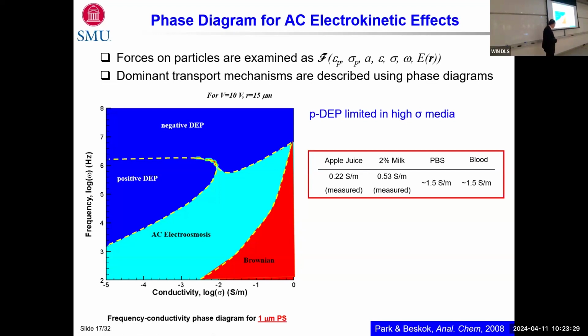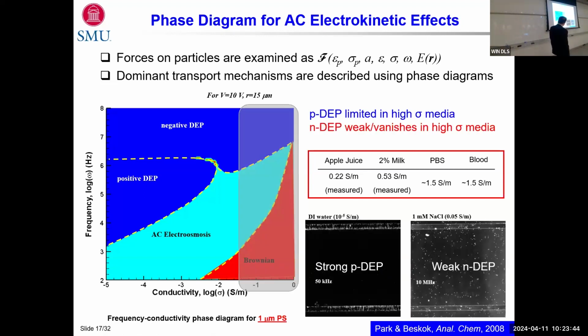We were trying to use this for sample concentration from apple juice and 2% milk. And those are basically the conductivities of those fluids versus blood plasma versus PBS solution. So obviously there are big differences. And you can actually see that in the DI water over here in low conductivities, I can see the very nice particle shading, but we lose the effect of DEP. We expected negative DEP, so I was hoping to see that these particles will be coming on top of the electrodes. These are electrode gaps here, but we didn't observe that. So obviously, DEP is losing its effectiveness, and that's a big concern because all physiological media is mostly like 1.5 S/m conductivity, and then this method may not be useful at all.